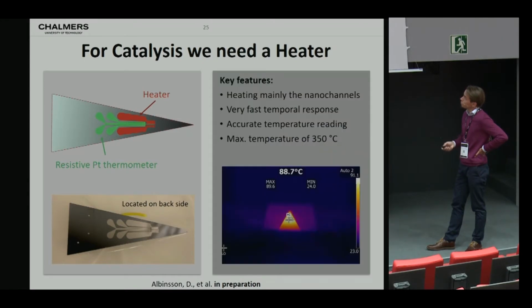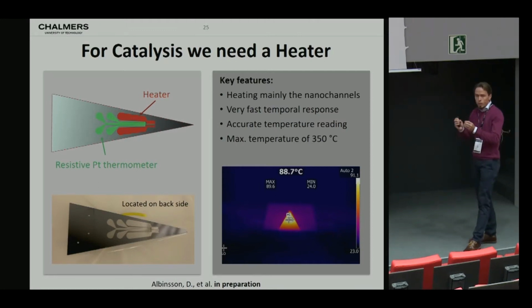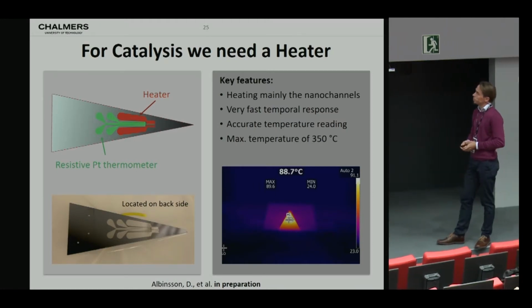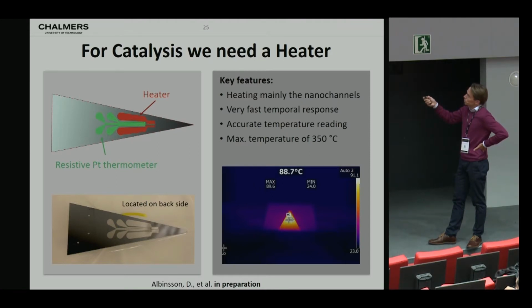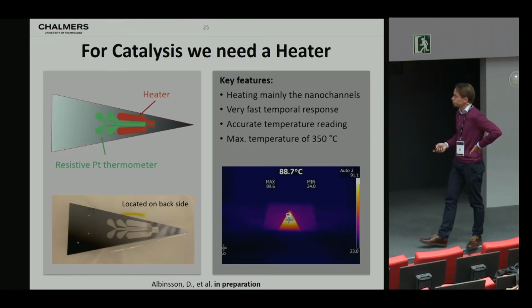So on the backside of our chip, we have implemented a resistive heater with the following features. It is supposed to and does mainly heat the nanochannel zone. Because of the small size of all this, we have very fast temporal response. We are also able to measure the temperature accurately by means of this resistive platinum thermometer structure, which is also grown on the backside of the chip. And we can reach a maximum temperature of about 350 degrees.